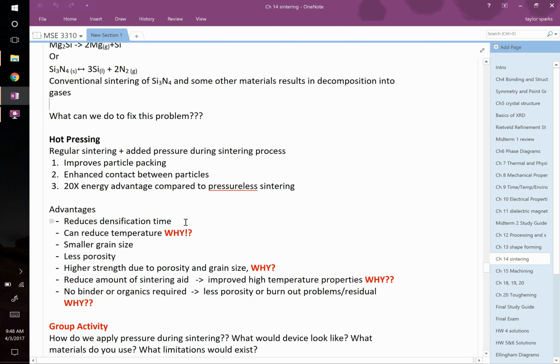Meanwhile, if you use a hot press, you're heating up that whole chamber, but because you're applying this load, you don't have to hold it for 15 hours probably. In fact, you can hold it for a couple minutes. So you can get way, way less energy consumption with these. It's actually pretty advantageous if you're talking about reducing energy in production. The power bill for some of these companies is pretty non-trivial. It's a pretty enormous amount of energy, right?